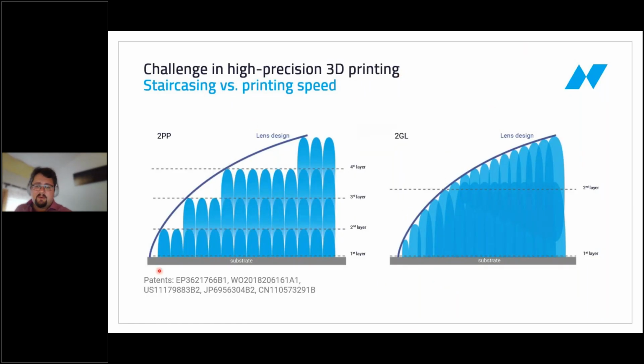So instead of going layer by layer and just switching the laser on or off at a specific power, you can now actually dynamically change the laser power in order to change the height of the layer while you are printing the layer. As you can see here in this sketch, but this is actually quite accurate, you can reduce the number of layers and still end up with a much smoother surface than you could previously. So this is called two-photon grayscale lithography because it has the power change in order to change the structure height in common with conventional grayscale, although as you could see, the details are quite different. But this is going to be important in a moment. This is implemented in the Quantum X line of products.